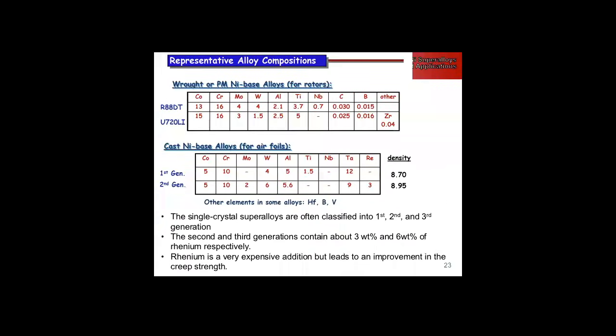If we look at composition - wrought or powder metal nickel-based superalloys for discs versus blades - they have quite a different composition. Significantly less cobalt and chrome, higher aluminum, so we have a higher fraction of gamma prime formers in airfoils than we do for discs.